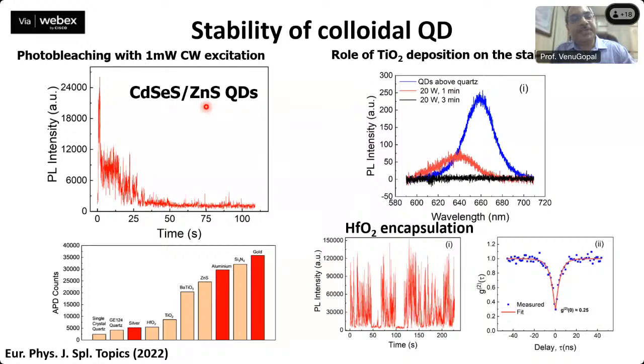Depending on the material we use, there is a degradation which happens because of the diffusion of chemical compounds inside the quantum dot, which reduces the size of the quantum dots and shifts its emission to blue, so shorter wavelengths. To avoid that, we studied numerous materials, both insulators and metals, to find out which give less scattering and more stability to the quantum dots or nanodiamonds, and eventually found that hafnium dioxide reduces the blinking effect.